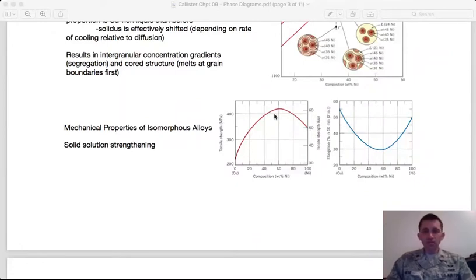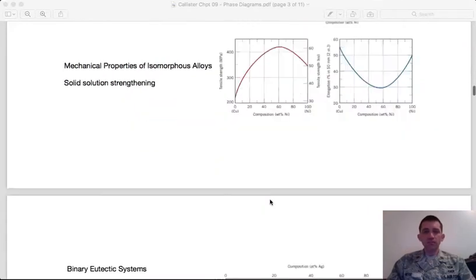And so I see the tensile strength peaks here somewhere around 40 to 60, say 60% in this case, which is about half and half, so you'd have a peak amount of lattice disruption. And normally, remember, tensile strength and ductility are inverse, right? So this is a good example of that, where just as I'm reaching peak tensile strength, I'm reaching the minimum of my elongation, or my ductility.